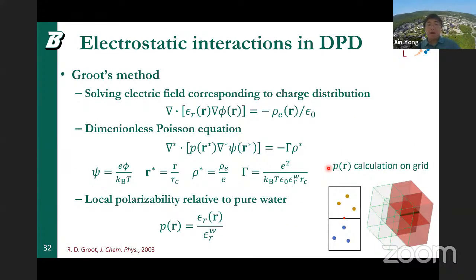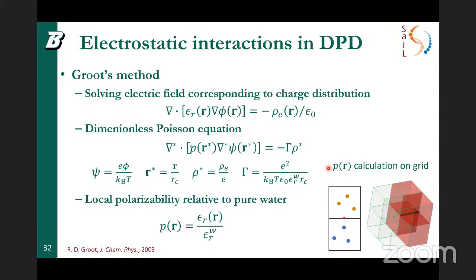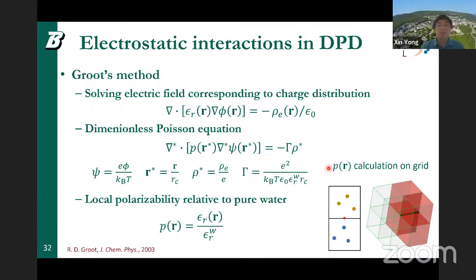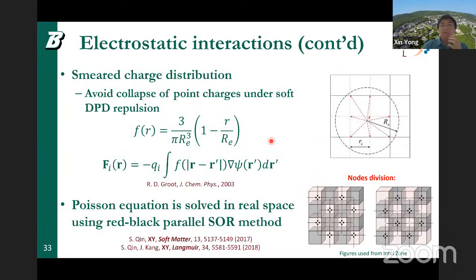So we try to explore this hypothesis using DPD. So here I'm going to add another ingredient to the DPD, which is the electrostatics. So we adopt a very basic model, which was developed by Groot, solving the electric field due to the charge distribution with the Poisson equation. And so what's important here is that this method we're picking is able to account for the dielectric contrast through this local polarizability parameter. And for this Poisson equation, the charge needs to be distributed in DPD to avoid the collapse of the ions under the soft potential.